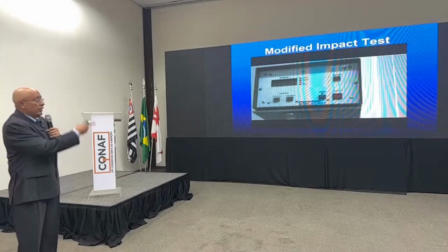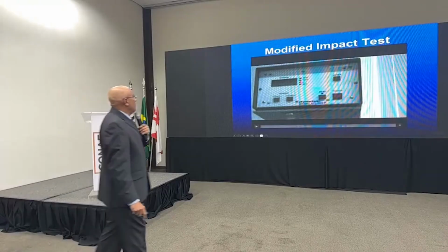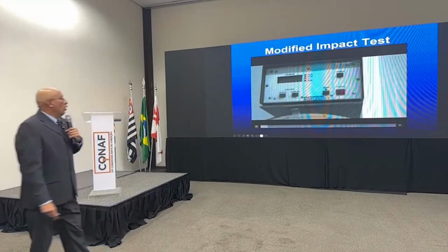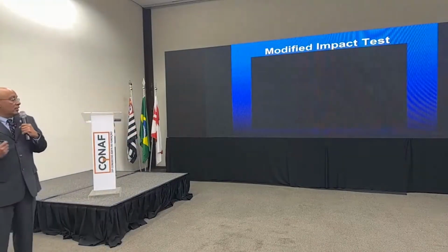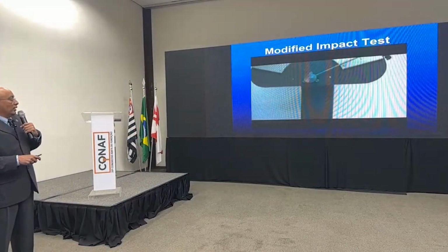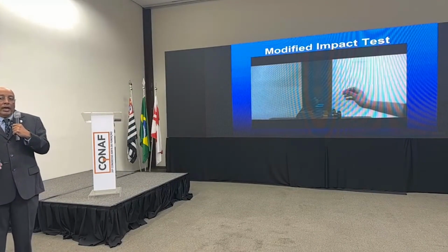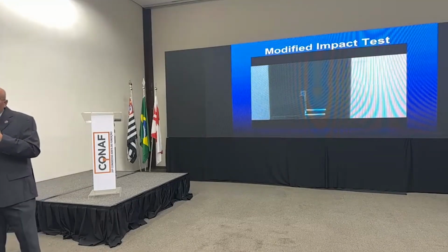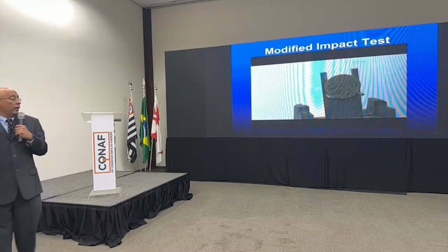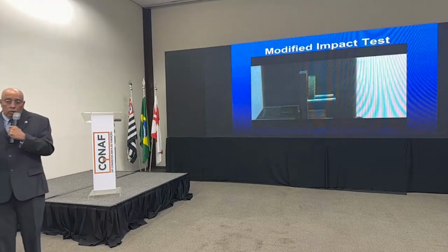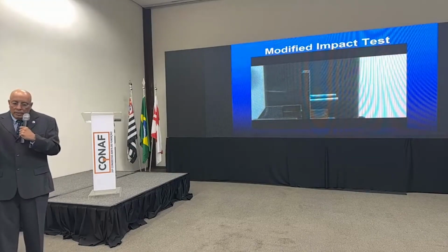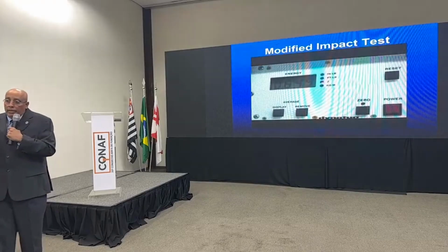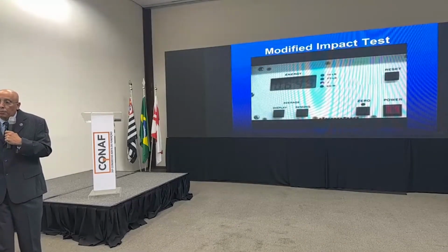So we prefer using this technique to show how we get the energetics to break that cookie before heating and after heating. Before versus after will give us an indication of whether that core in the mold will shake out. And the reason for this is if we are shaking out all day, we're not making any money. It's a productivity issue.